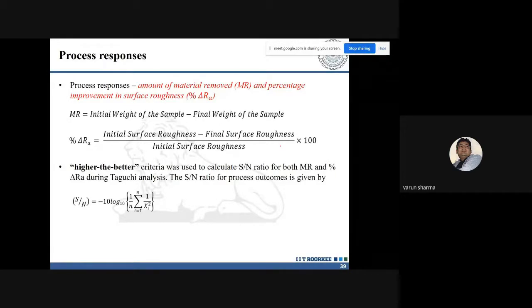Now, the reason we do not measure over here the final surface finish, and do not report it that way, is because it depends upon a number of parameters. For example, if my initial layer thickness is 0.3, I will have more scope to remove the material. If my initial layer thickness is 0.1, the staircase effect would be less, and I will have lesser scope for material removal for the same kind of abrasive media. So we want both: the material removal should be higher, and the percentage improvement should also be higher.